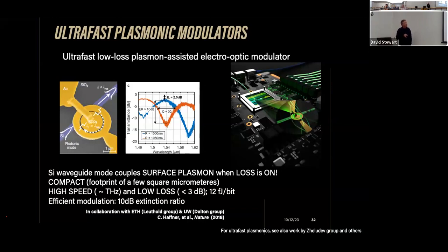So if you send the signal through this silicon waveguide, and the frequency of this mode doesn't coincide with the frequency of this ring resonator, then it simply goes through without any losses. Then if you apply voltage to change the refractive index, so that now the frequency of this mode matches the frequency of this signal, then there is strong coupling and light doesn't go through. You clearly have this switching on and off, and it turns out that the extinction ratio is quite high, 10 dB, but most importantly, the speed with which this device operates is in the terahertz range. And this is the magic number.